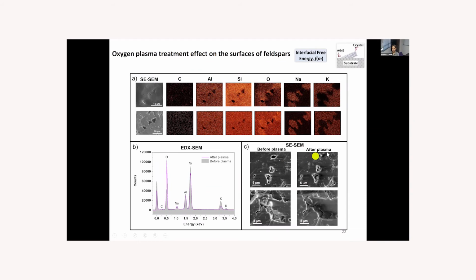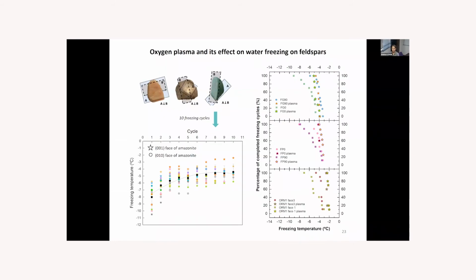And also in the morphology of the samples, we could see that the surface looked cleaner, with fewer particles and fewer impurities. And we have performed many experiments on the different cuts of feldspar. So there's this pink mineral, this gold, and green one. And we have performed many cycles of freezing of water films on top of the cuts.